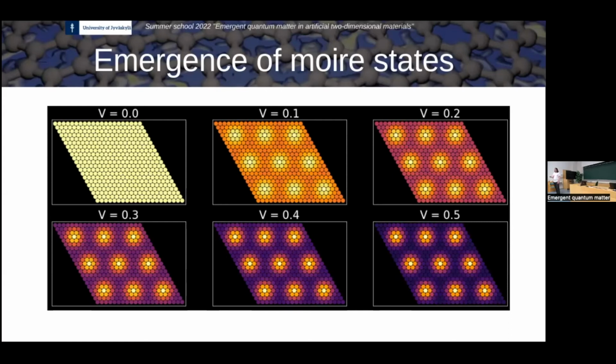Let me emphasize that this kind of picture of quantum dots works very well for twisted TMDCs, but for twisted graphene, it is actually much more complicated. In twisted graphene, one shouldn't think so much about isolated quantum dots, and one should think more in terms of the flat band being pseudo-Landau levels of an artificial gauge field. In particular, in graphene, the flat bands can be understood as Landau levels of a non-abelian gauge field that is driven by the modulation of the hopping in the unit cell.